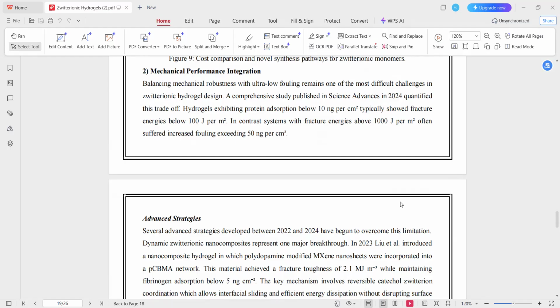Conversely, hydrogels with fracture energies exceeding 1000 joules per square meter often exhibited significantly higher fouling, with protein adsorption exceeding 50 nanograms per square centimeter. This clearly shows that improving mechanical strength often comes at the expense of anti-fouling performance.